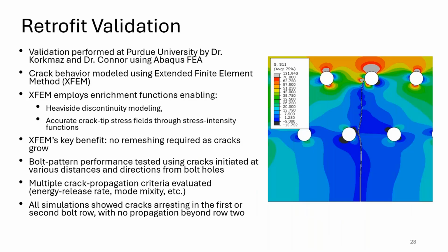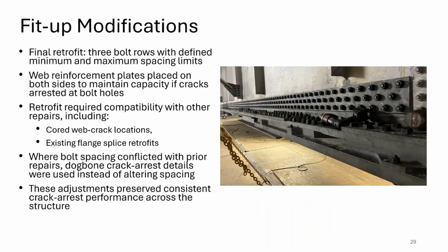And then finally, once we had the bolt pattern that we wanted to implement, the last thing was to provide a series of modifications so that this retrofit is compatible with the other retrofits already in the structure. As I said before, the final retrofit is 3 bolt rows with a defined minimum and maximum spacing limit, and web reinforcement plates placed on each side in order to maintain capacity of the web if a crack were to emanate from the web to flange and propagate into the web.